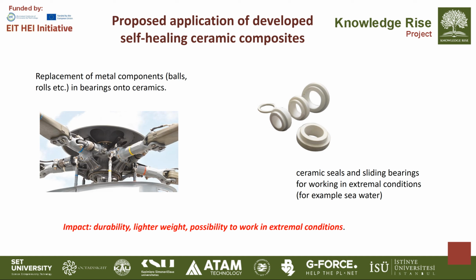Ceramic ball bearings from silicon nitride are widely used in aerospace and high-speed mechanical systems because they are lighter than steel, have lower friction, and resist corrosion. Yet contact fatigue and surface microcracking remain critical failure modes under extreme speed and fluctuating temperatures. Developing the self-healing composite from both silicon nitride and zirconium nitride into bearing systems can drastically improve service life and reliability for these ceramics.